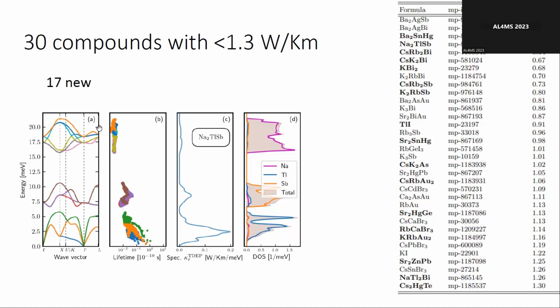And it's quite interesting when we looked at the features. We also found that the big electronegativity difference was maybe the most important feature. And you can also see that here in the way the band structure looks. And if you look at the atom projected density of states, you see here that the thallium is essentially just vibrating, is rattling. All the 3 atoms are essentially rattling. They just vibrate independently, more or less, which was an interesting result.